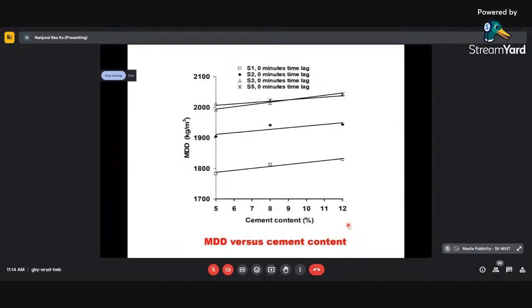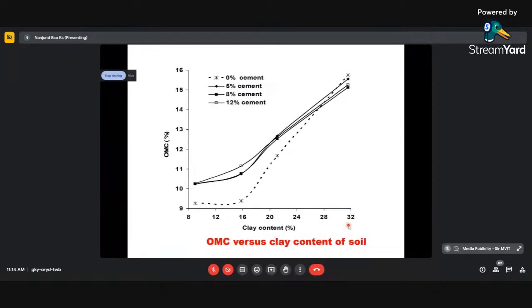This is again the maximum dry density, the relationship between maximum dry density and cement content. Again, for the four kinds of soils that we have discussed, you will see as the cement content changes, what is happening for the different soils at different maximum density. This is again optimum moisture content and how it varies with the clay content in the soil from a small quantity to as high as 31%. So with different cement percentages as a stabilizer. You also have 0%, which means unstabilized rammed earth, and that is the least you can see here.